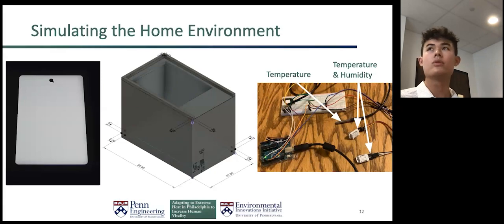And then for the roof, we used this aluminum substrate that you see on the left. And these are nice for two reasons. First, they offer us a standard substrate so we know that everything is controlled trial to trial. And second, they simulate real world conditions because metal roofing is used in a lot of different places around the world, especially temporary housing like refugee camps. And some of these places are in the most heat vulnerable areas on the planet. And it's important that we can develop coatings that are able to adhere well to metal surfaces in addition to more common roof materials in the US.